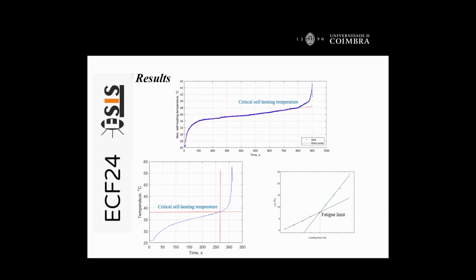Okay, when we find this value, the critical self-heating temperature, we can put it in a plot of temperature versus load, or we can convert to stress, and we can have these points, and we can adjust two lines, two curves, and this point is the fatigue limit. Okay, in this case, we can obtain the stress or load for the fatigue limit.